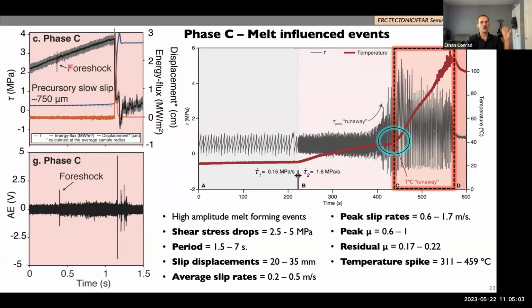In this phase, we see way more interesting things, just because the events are larger, so you really just have kind of better resolution too. But we see a foreshock that's happening before the event. In the AE, that foreshock seems to kick off some different behavior in the AE signal. Then with the slip event, we have more displacement here between 2 and 3 centimeters. We see the reversal of the displacement, so it's turning and then bouncing back because of the inertia of the event. And then we see the much higher energy flux associated with each event.